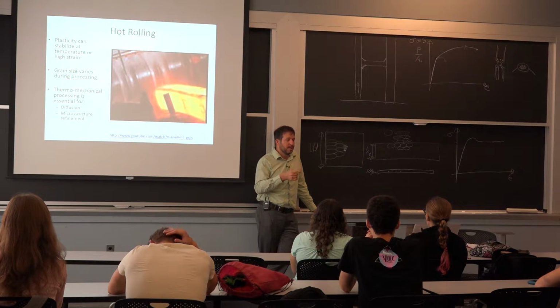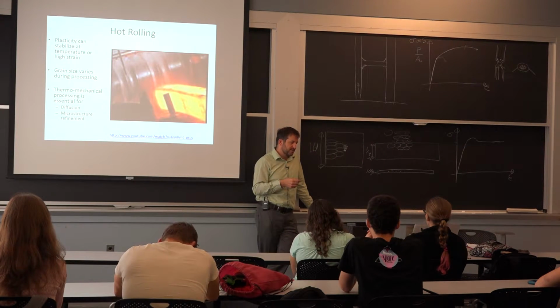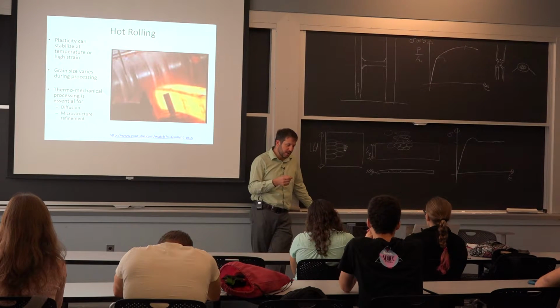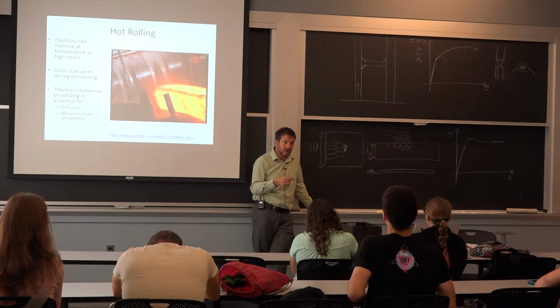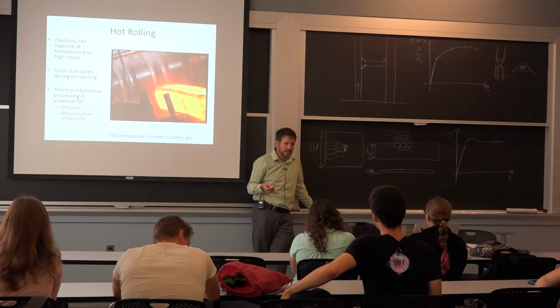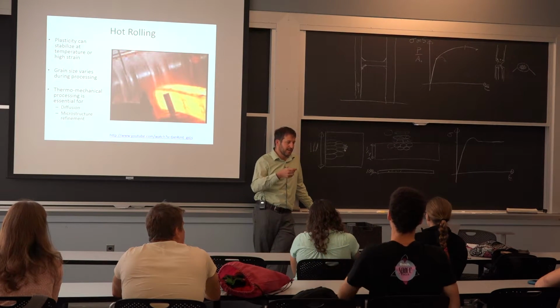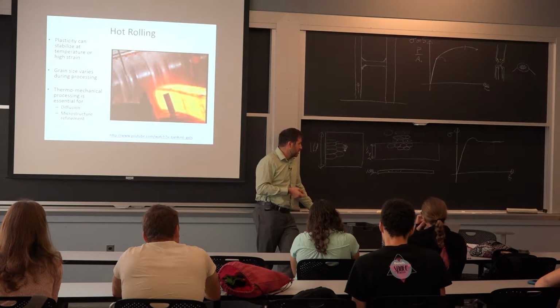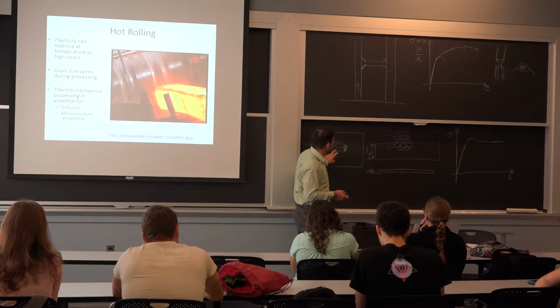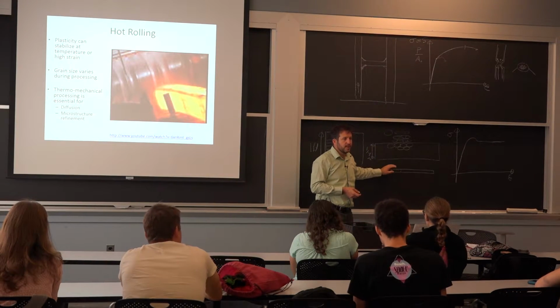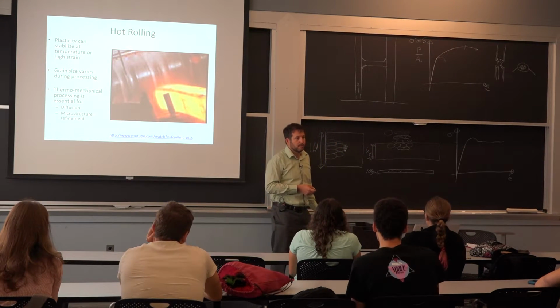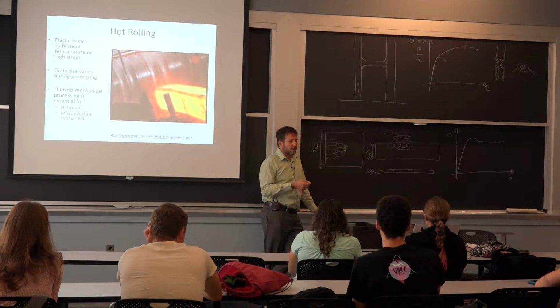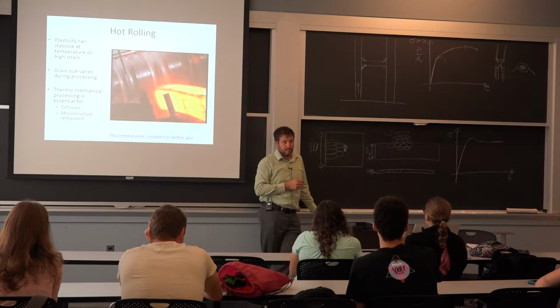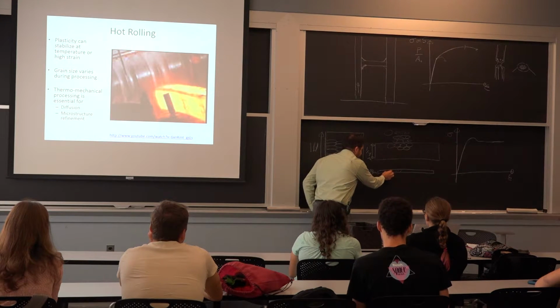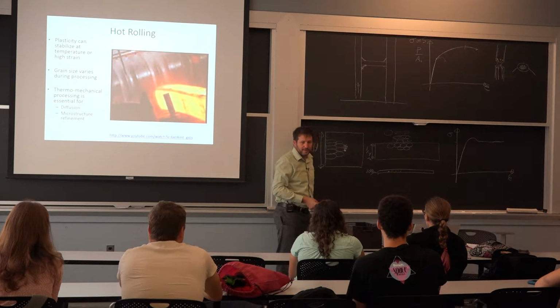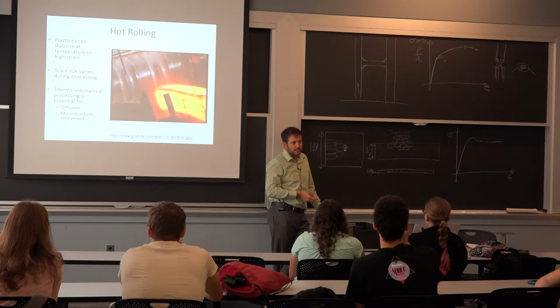So that's where, if you're looking into especially aluminum alloys, the problem with aluminum is it's so sensitive to oxidation. We know at ambient temperature it's always oxidized. When we cast it, it does tend to oxidize a lot as well. So when you do this entire process with aluminum, you end up with a lot of inclusions in your material. And if you're trying to do a small wire, it'll break on you because now you have essentially a hole, practically speaking, in the material in an area that you don't want it.